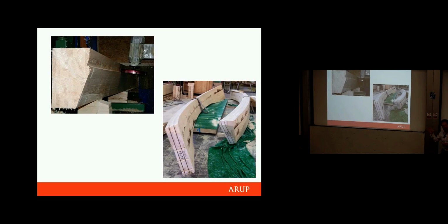Now, there's a disadvantage in doing that. I told you wood's fibrous. Anybody want to suggest what the disadvantage might be? Yeah, exactly. If you make a nice doubly curved twisted, properly two-way laminated beam, all the wood fibres are following the curvature. But if you do this, all the wood fibres are straight. And so now all the fibres are running out the side of this. And remember I told you that a bundle of drinking straws is 5 or 10 times weaker perpendicular to the grain than parallel.